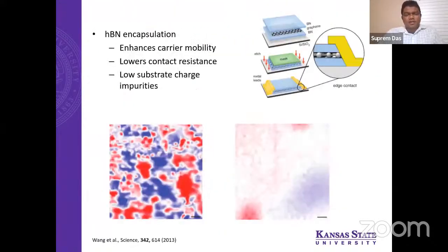Now, one of the great discoveries in 2013 was by Lei Wang et al. at Columbia, New York. What they did was a very smart way of putting the contacts. Typically when you have a transistor, you put the contact on the graphene itself, right? So if you have multilayer graphene, only your top layer is contacted to the metal, but that way you may not necessarily modulate all the charge carriers in all the layers.